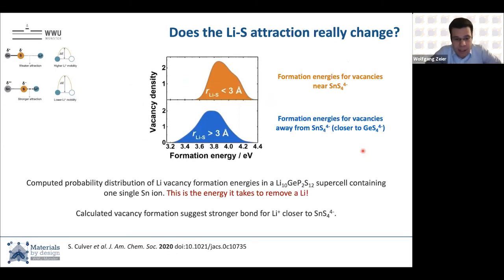So something that Ben did, which I really like, is the idea of let's look at how much energy it takes to remove a lithium. Does the lithium-sulfur attraction really change? We can calculate bond polarities and things like that, but does this sulfur-lithium attraction really change? And so he built a supercell of this LGPS, or the germanium phase, and put one single tin atom in there. And then calculated the vacancy formation energy, so the energy it takes to take a lithium out.